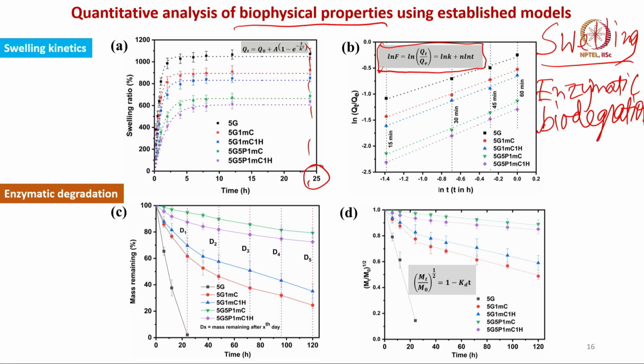So, at different time points you can get the kinetic parameters by following the simple kinetic rule. As far as the hydrogel composition is concerned, this is the 5% gelatin, right. It can have a swelling ratio as high as 1000%, but with modification of the hydrogel composition, 5% GelMA, 5% PEGDA, 1% carboxymethyl cellulose, 1% hydroxyapatite, this has been reduced to 550% or so.